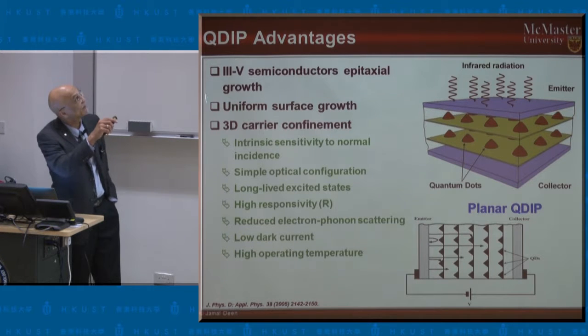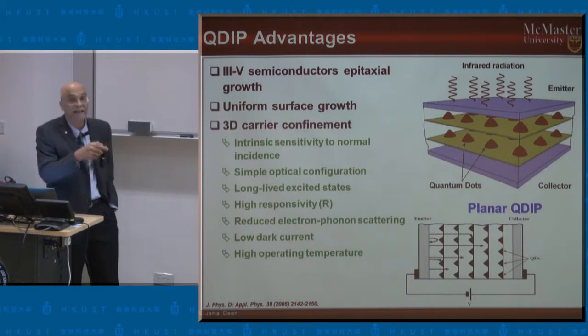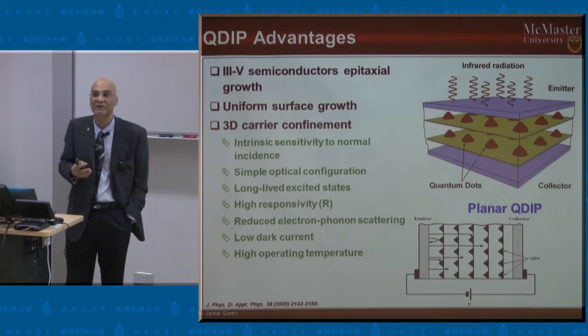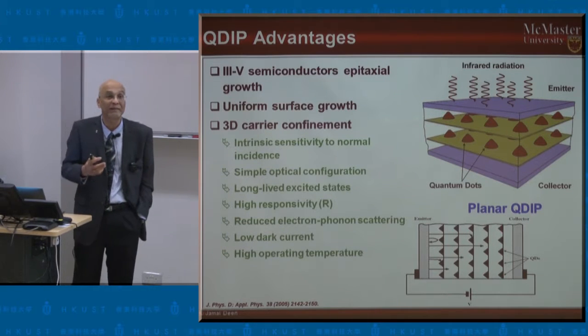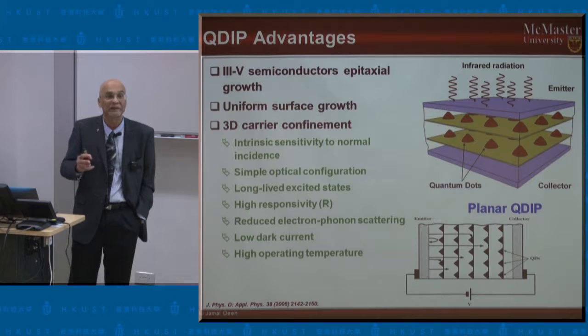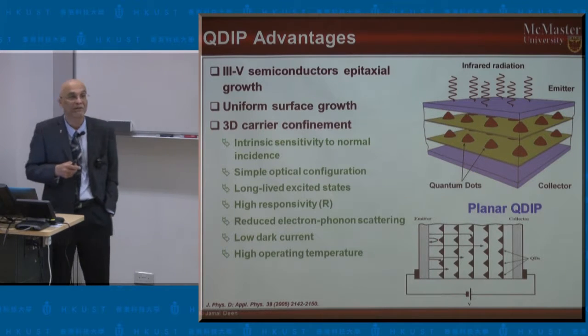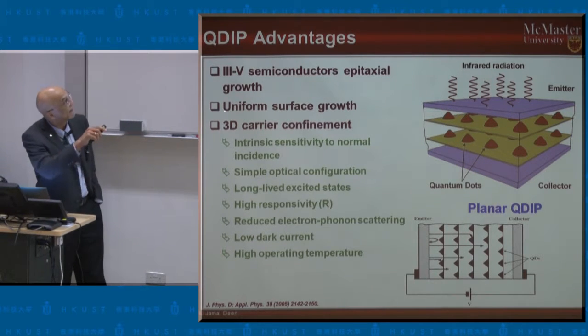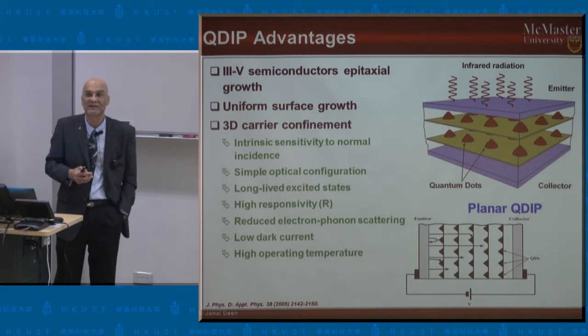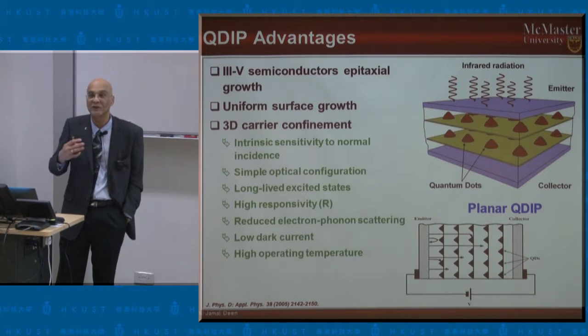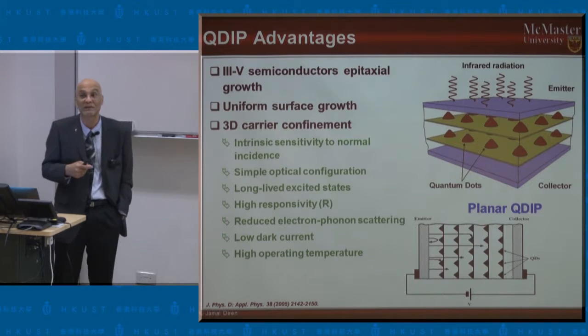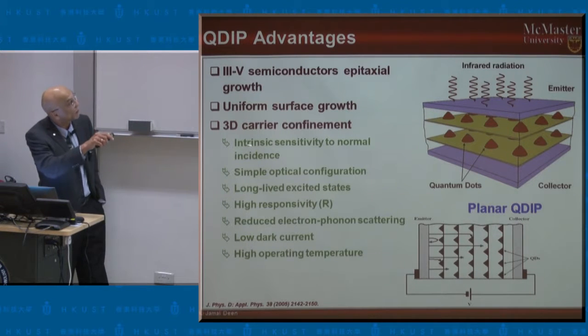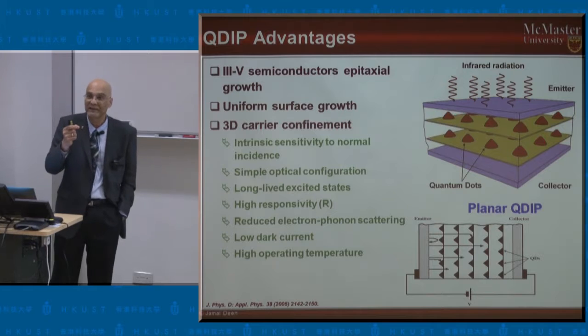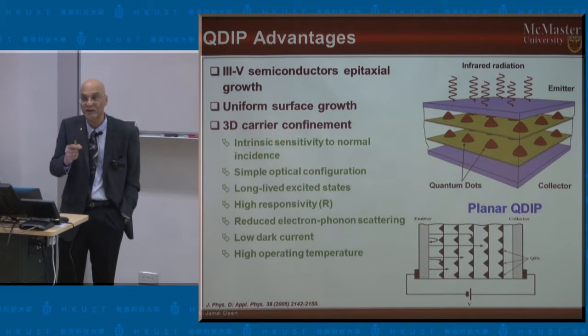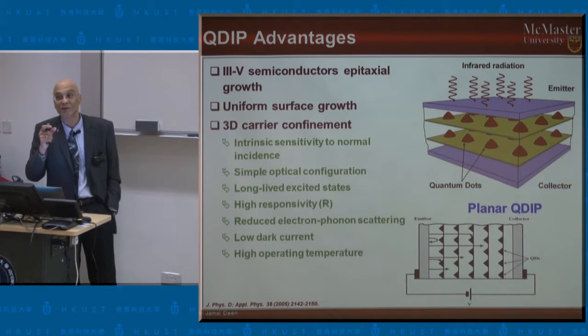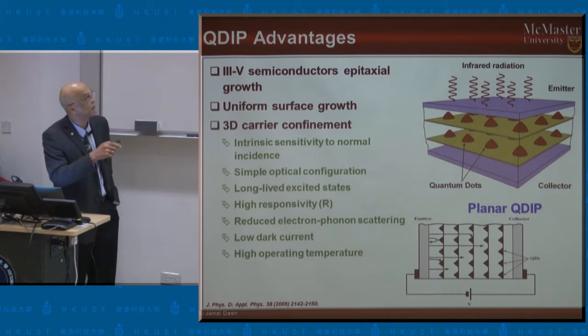So they're typically made using III-V semiconductors grown in an epitaxial system. Examples of epitaxial systems would be molecular beam epitaxy or MOCVD, metal organic chemical vapor deposition. These are the two common ones. We can have uniform surface growth, so this is a well-developed technology that allows us to grow repeatable and reproducible QDIPs. And one important aspect is that because they are small structures, we can have 3D, three-dimensional carrier confinement in these quantum dot devices. So this is really very important.